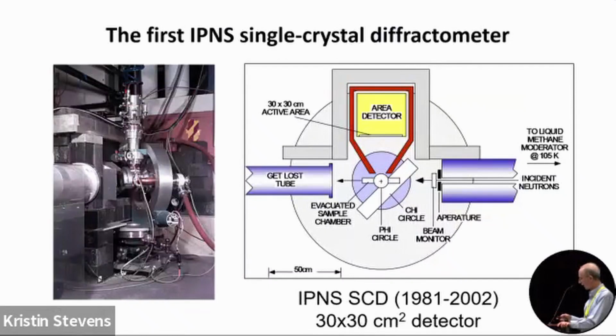So here's a drawing and a photograph of the first IPNS single crystal diffractometer. The sample is here, and the incident neutrons come in this direction. Actually, we moved the instrument from that hutch to a different beam line, and now we're at 9.5 meters from the liquid methane moderator. And then at 90 degrees, there's a 30 by 30 centimeter active area detector.